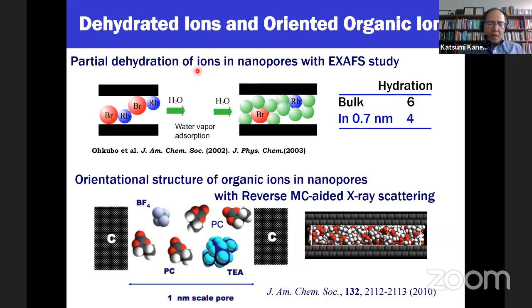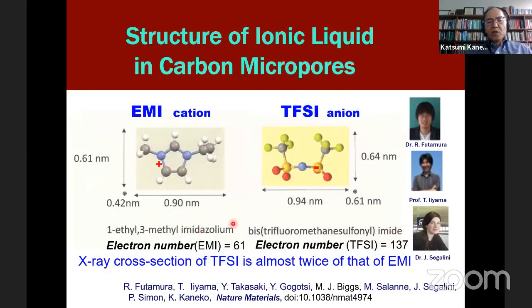Then we moved on to the confined organic ions. In such a case, we used tetraethyl ammonium. In this case, these ions in the highly confined situation showed some very unique orientational structure. At that time, we used reverse Monte Carlo aided X-ray scattering. But I was asked by Patrice, the supercapacitor scientist, and also Yuri Gogotsi, to support the supercapacitor work. Then we started nearly 10 years ago.